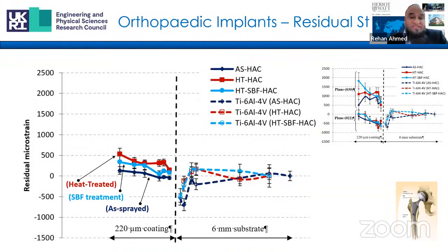Once the multiple peak analysis is conducted, the average microstrain in these coatings can be analyzed to give an overview of the overall stress field, as shown in this slide. And the slide also shows the changes in the through thickness residual strain profile caused after the heat treatment and subjected to simulated body fluid conditions. Further changes in the residual strain profile can be expected due to mechanical loading during the life of the implant. So in conclusion, what we can say is that the residual stress profile is dependent on the type of analysis or the type of neutron diffraction or non-destructive analysis, and changes due to post-treatment and bioactivity in these hydroxyapatite coatings.